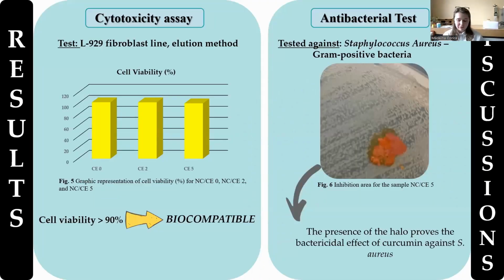Regarding their bioactivity, the samples were tested for their cytotoxicity as well as for their antibacterial effect. Cell viability obtained for the plain nanocellulose as well as for the selected samples containing different amounts of curcumin extract had values greater than 90%, deemed the samples biocompatible with the cell line used in the test. For the antibacterial test presented on the right of the slide, the sample with the highest amount of curcumin extract was considered and was tested against Staphylococcus aureus with positive results, as we can see from the halo present